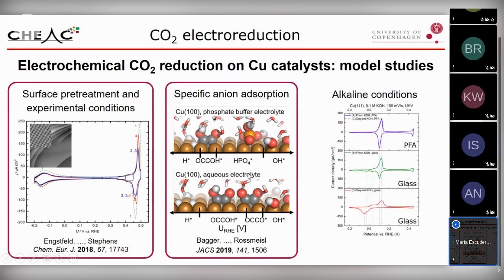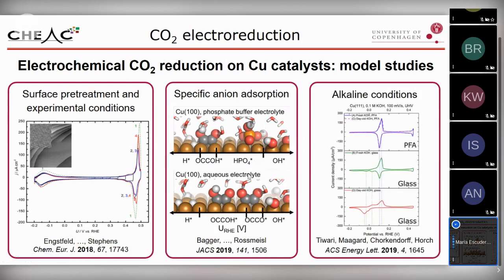And also a recent work from Ib Chorkendorff and Sebastian Horch at DTU showed the influence of just the electrochemical cell. So if you are in alkaline conditions and you work in a glass cell, there are certain contaminations that are going to affect your performance. And thus, for that reason, you need to avoid working in a glass cell in the cases that you are working in alkaline conditions. So that was very inspiring for us.